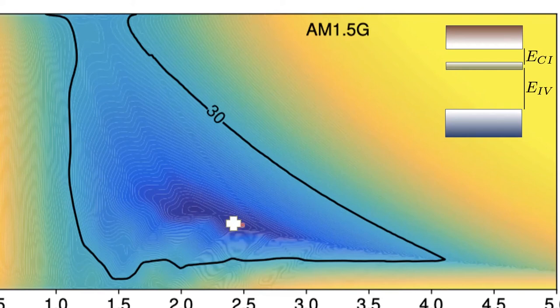So the maximum efficiency of about 47% occurs here at about 2.4 eV. And I just want to show you, so first of all, I want to say this calculation, for a couple technical reasons I'd be happy to describe, is not accurate for intermediate bands down in the middle. It's unnecessarily pessimistic. So please don't pay attention to that poor region, but up here it is a quite accurate optimal efficiency that we can achieve. The color scale being the efficiency that could be achieved by these devices.